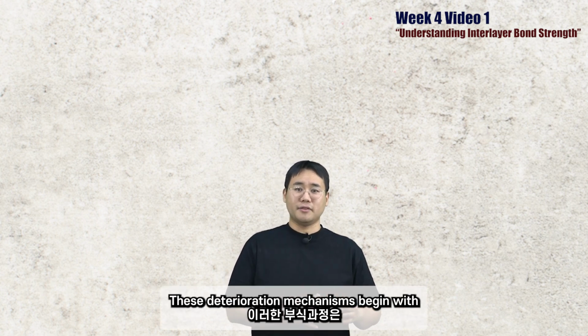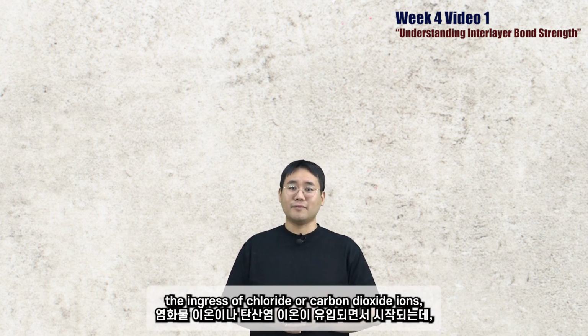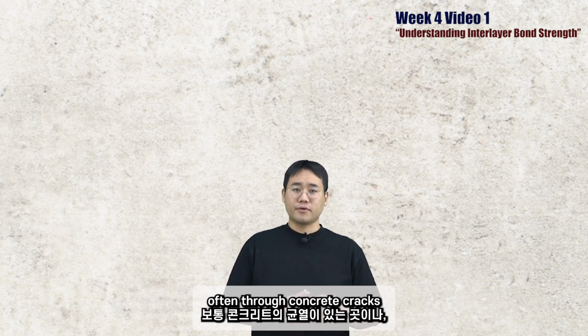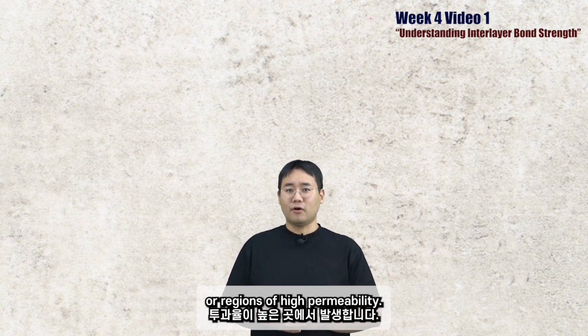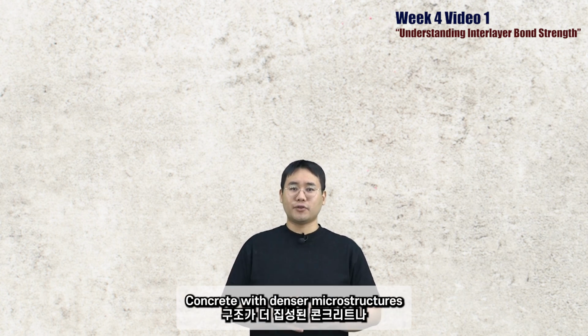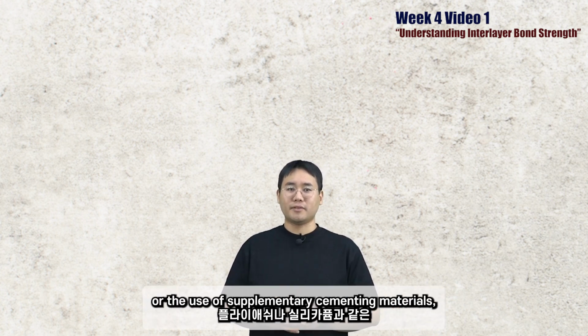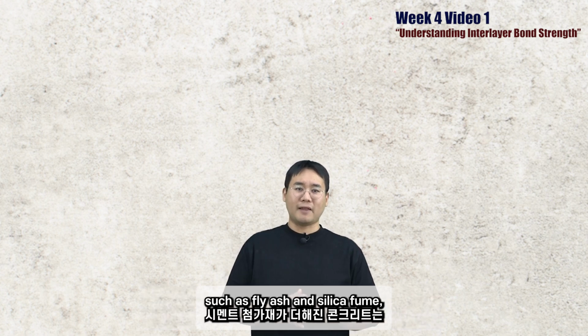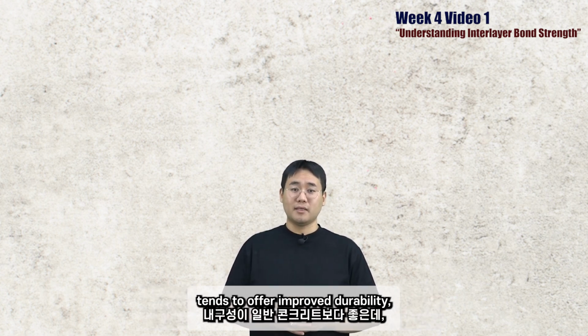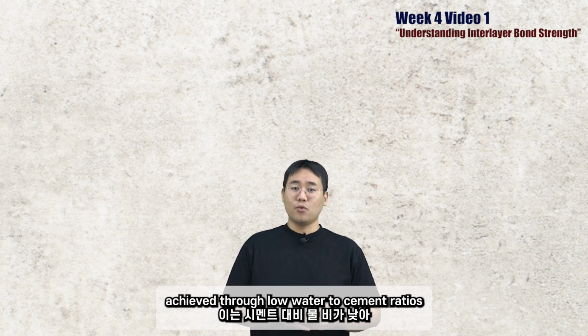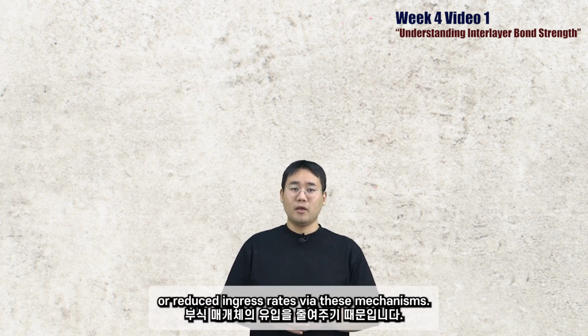These deterioration mechanisms begin with the ingress of chloride or carbon dioxide ions, often through concrete cracks or regions of high permeability. Concrete with denser microstructures, or the use of supplementary cementing materials such as fly ash and silica fume, tends to offer improved durability, achieved through low water to cement ratios or reduced ingress rates via these mechanisms.